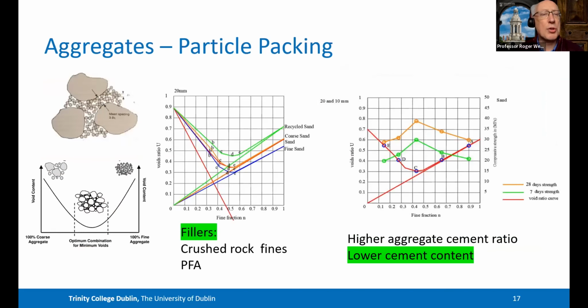And to illustrate this point of some research we've been doing, the diagram on the left will indicate to you how if we use only stone or only sand, we don't end up with the best void content. Remember that the smaller the quantity of voids, the less cement we have to use in order to fill up those voids. So if you look at the central graph, for example, one of my postgraduates was looking at using different types of sand in different quantities, in different fractions with a 20 millimeter aggregate in concrete to see how best we can optimize it. And as you see, you move from the green line to the orange line, we're reducing the voids and therefore reducing the amount of cement. In other words, we're optimizing the aggregates.